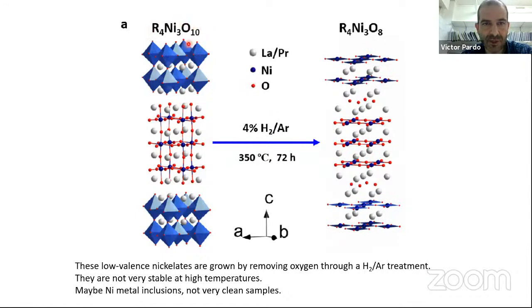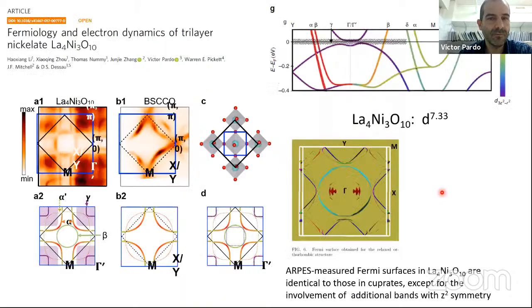They create first the Ruddlesden-Popper, and then they remove the apical oxygens. So basically what you get rid of is these apical oxygens here. So you get the square planar environment around the nickel, this hugely Jahn-Teller distorted environment that leads to the splitting of the eg bands as we had in the cuprates. Yeah, but these samples, they are not very clean. They even have nickel metal inclusions. The grains are really huge. The intergrains are really huge. So these samples are not very clean because they are difficult to make.